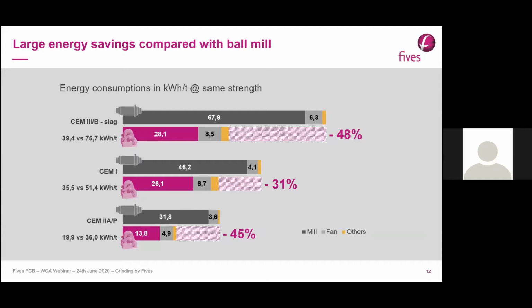The difference can be explained either by the grindability of the mix or the fineness that has to be reached. The main gap here, the major saving, is due to the fact that the efficiency of the grinding bed, compression grinding, is more efficient than ball mill grinding. And you see that most of the saving is due to the fact that the specific energy of the mill only is much lower for the Horomill compared to the ball mill.